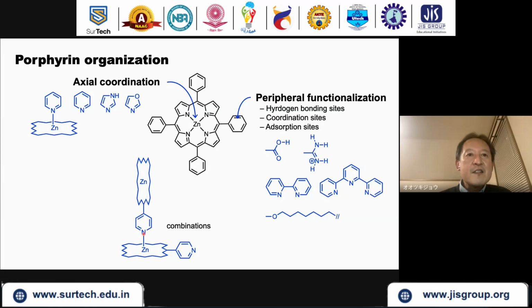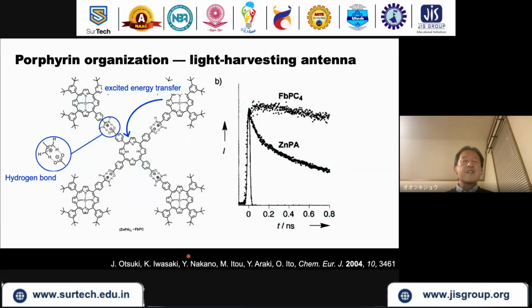In this case, the porphyrin itself assembles into higher order structures. Some of them I'll tell you about soon. This is an example of a hydrogen bonding assembly of porphyrins. Here we introduce an amidinium group and a carboxylate group here and here. And we put zinc ions into the surrounding porphyrins, but not at the center, so that the pi electron energy level is different. This has a higher energy, this has a lower energy. So on excitation, energy transfer happens from the peripheral site to the center.